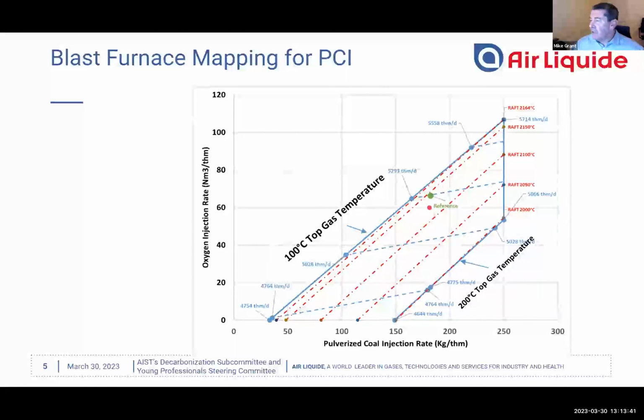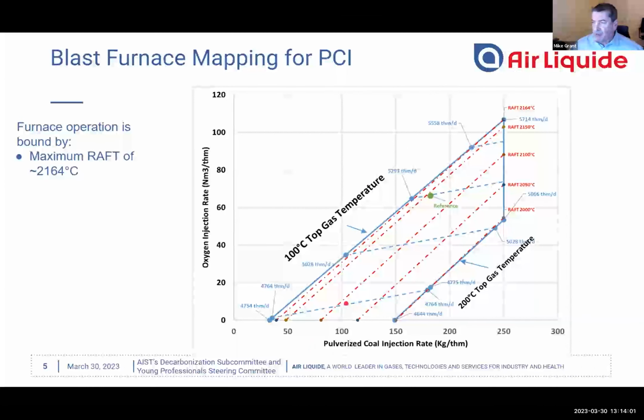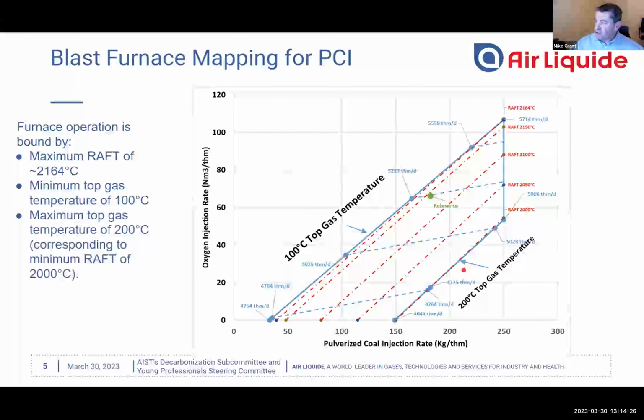We can move around in this shape and we can bang up against these limitations. But if we increase our oxygen and increase our pulverized coal injection, theoretically, we can reach this point up here, which is our maximum productivity. The furnace operation itself is bound, in this example, by a maximum raceway adiabatic flame temperature of 2164 degrees Celsius, which follows the same line as this minimum top gas temperature, which is actually the true limitation. It just happens to be the same as the raft temperature. We have a minimum top gas temperature limitation, and we have a maximum top gas temperature limitation. These are pretty classic limits that are defined by most operators. And you can see also this maximum top gas temperature coincides with the minimum flame temperature.